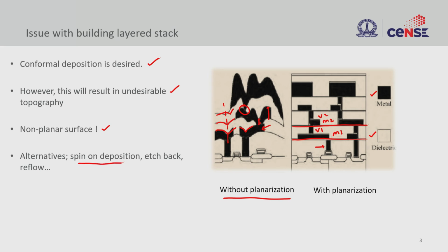There are some alternate methods to address this topography issue. There is spin-on deposition, and there is etch-back and reflow. But there are disclaimers once we start using these. For instance, you cannot use all the materials that you require as spin-on deposition. You can deposit dielectrics using spin-on, but you won't be able to do metal deposition using spin-on. Similarly, reflow means you nearly melt the material. Once you melt a solid material, it tries to reflow and then becomes flat.